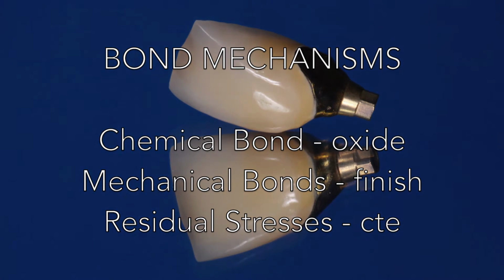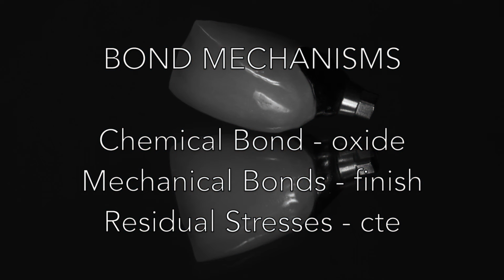Alright, so just to recap, we talked a little bit about the oxide layer and how important it is to use a Ti bonder in order to optimize your oxide layer. Using a cross-cut carbide bur for metal finishing will prevent you from folding the metal over itself, and then the residual stresses are sort of just taken care of for you because with titanium, the CTE is pretty much the same in any titanium that you're going to get, so your porcelain should line up well in terms of the residual stresses.